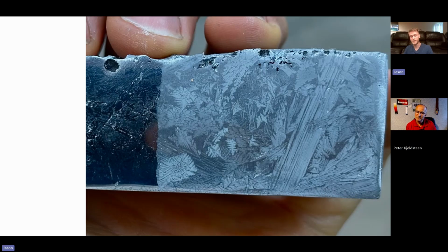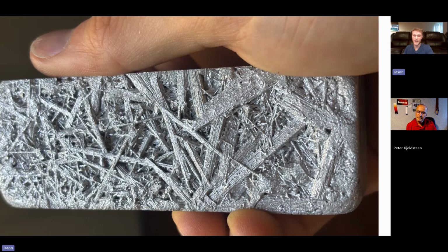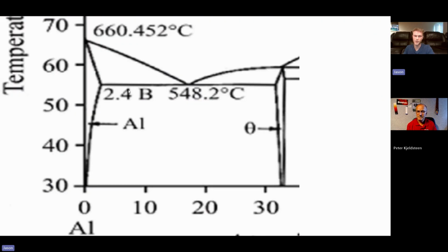And so this is a nuance with the phase diagram that I wanted to discuss. I'll emphasize it more in a bit, but you could be anywhere in this alpha theta coexistence region, and you can have drastically different microstructures. This phase diagram is very generic, and it says that this whole region is alpha theta coexistence. But this side compared to this side is going to have completely different properties, completely different microstructure. And even if I were to stay at 30% copper, if I were to change the heating profile, I'd have completely different microstructures. So the phase diagram is very generic, and there's a lot of nuances that you have to keep in mind when you're trying to interpret them for use in your materials.